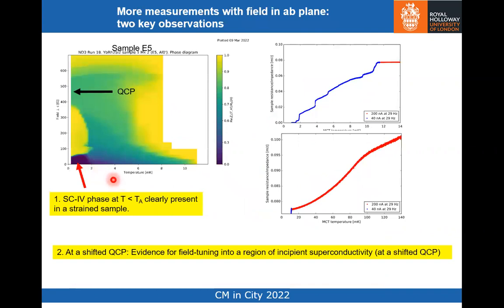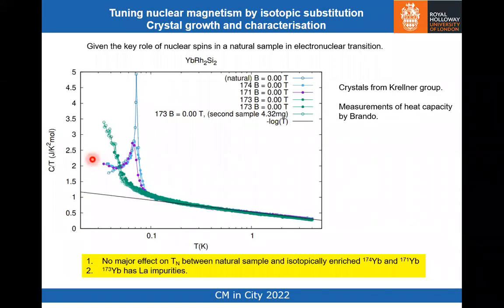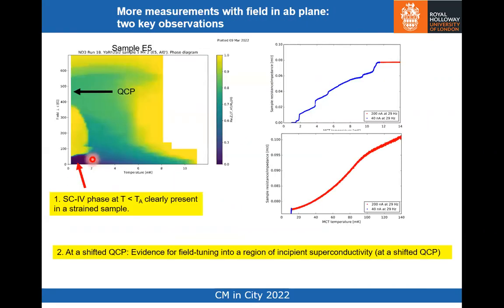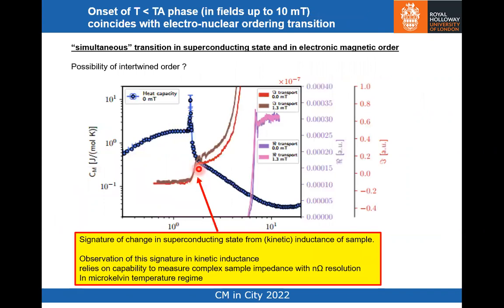Now, on a better quality sample, we need to explore the alignment of the disappearance of the superconducting onset with the evolution of the heat capacity. But the physical nature of the system is very different as a function of magnetic field, right? So in zero magnetic field, you would just have, according to our simple piece of thermodynamics, the spin density wave order. But as you apply a magnetic field, you get this growth in what we're calling the paramagnetic component parallel to the magnetic field, which is ultimately going to lead to the destruction of the spin density wave state. The destruction of that spin density wave state is happening at a higher magnetic field than the destruction of superconductivity.